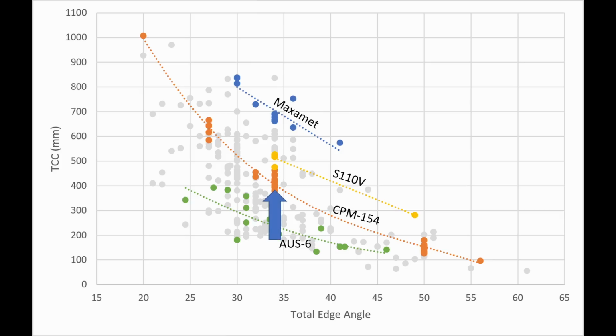When it has a 34 degree edge angle, that's only 3.5 degrees per side greater. That same 400 millimeter of cardstock is measured with the very wear-resistant S110V with an edge angle of about 41 degrees. If we give CPM 154 a 27-degree edge instead, just like we started with the Aus6, it matches Maxamet with a 41-degree edge. So small differences in sharpening can make big differences in the result of an edge retention test. This is why it's very important when we make steel and heat treating comparisons that we have identical edges. Identical. Because if it's 10% different edge, you're going to measure a 10% difference in cutting performance and edge retention, and you're going to say that was because of a difference in heat treating, when in fact it was not.